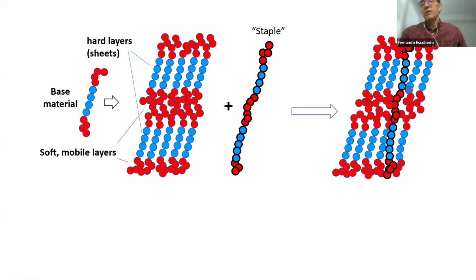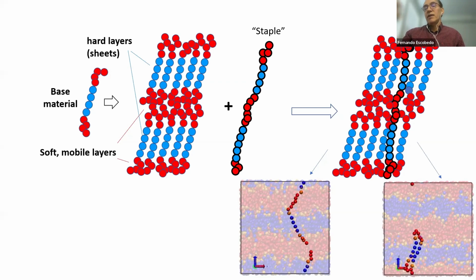Of course, if you put this staple into the system, you wouldn't necessarily expect that the molecule will stretch like this. You can also have these loop conformations. The one on the rightmost figure will be ineffective in promoting this coupling between the layers. But according to our calculations, you can expect that at least 38% of the chains will have this bridging conformation and will be effective in doing this stapling of the layers.